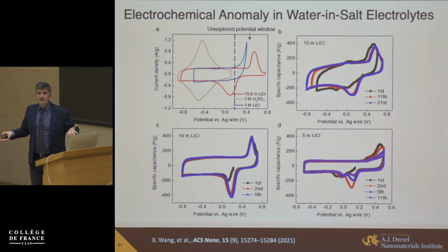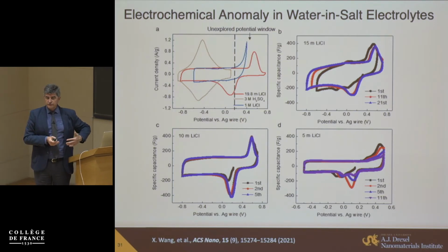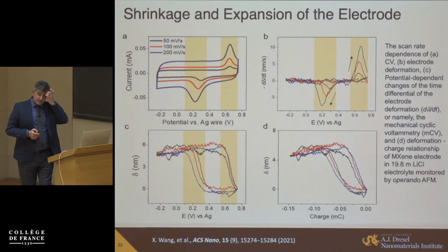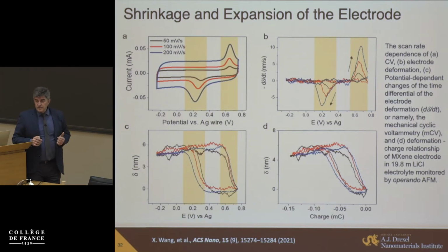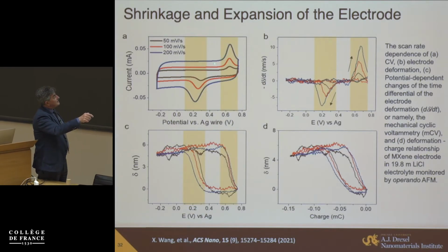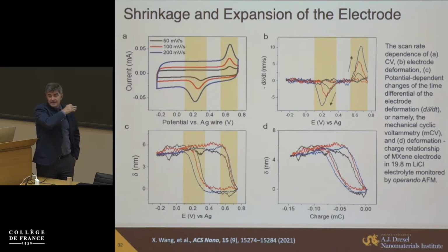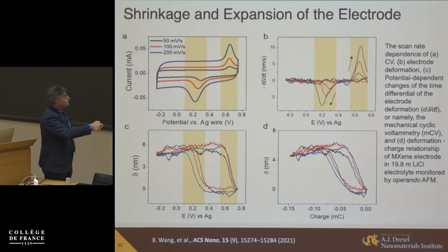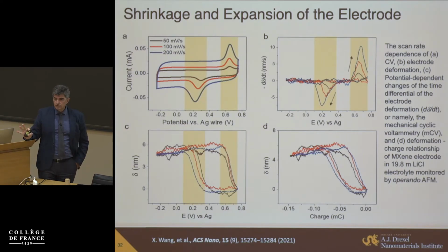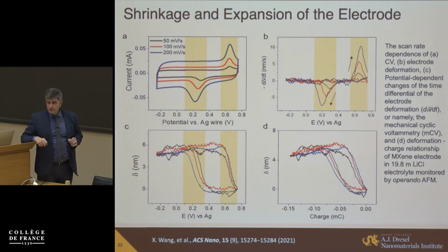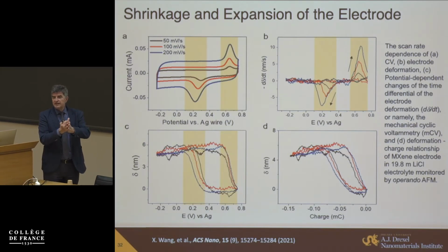So what happens? Initially I thought it must be a redox couple, or intercalation and deintercalation of anions, because we're in a positive range here. And we actually used a bunch of techniques, including QCM and others, to show that the mechanism appears to be very different. In fact, what happens when we see the charge capacitance here? We actually completely discharge everything from between the layers. If you look at mechanical changes, you see the electrode simply shrinks to zero, to a virtually dry state here. And then at a certain positive potential, there is a rush of cations out. So what happened? Anions don't intercalate at all within this range of potentials. But since we apply sufficiently high positive potential, all lithium ions, solvated with on average 2.5 water molecules per lithium, rush out. And the electrode simply closes, collapses.